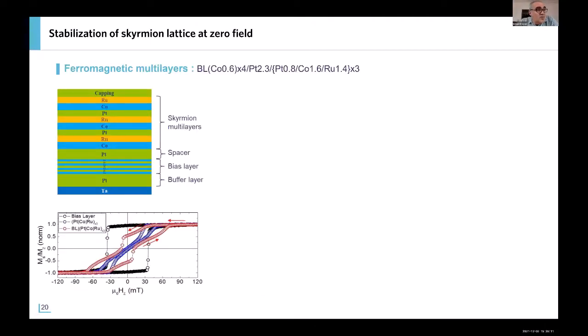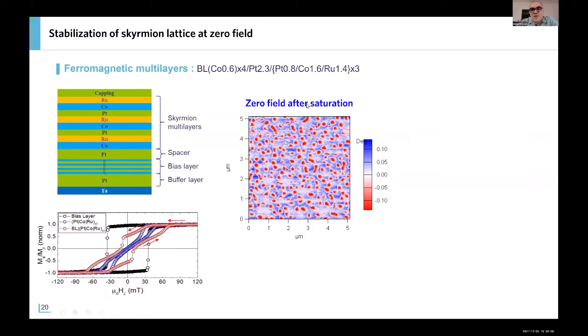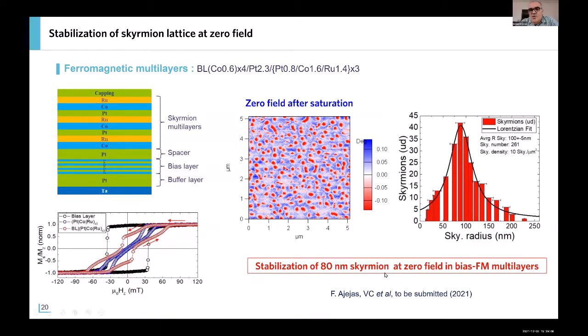Then another issue that came out today in the research for skyrmions at room temperature is that even if we do not need in multilayers a very large magnetic field, in general we do need a perpendicular field of a few millitesla or a few tens of millitesla. And for the potential application, it is important to have no magnetic field. So for that, we prepare magnetic multilayers, in this case platinum, cobalt, platinum, but including what we call the bias layer, composed of symmetric platinum, cobalt, platinum layers, which in fact create an effective magnetic field generated by the electronic interaction between these bias layers and the bottom magnetic layer. And this allows us, without field, after saturation, to have the stabilization of magnetic skyrmions with, in this case, for this parameter, skyrmions that are about 80 nanometer in diameter, but at strictly zero magnetic field applied.